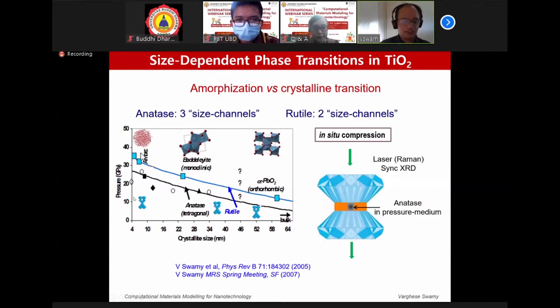And eventually it amorphizes. But if you start with a slightly coarser anatase nanoparticle, what happens is that the structure straight away transforms to the monoclinic structure, the high pressure phase. So this is a crystal to crystal transition, here a crystal to amorphous transition. Now, if you go to much coarser size, bigger than 50 nanometers and up to micro particle size, if you squeeze anatase in this diamond cell, you will see it transforming at lower pressure to the alpha PbO2 structure, which is the correct transformation as predicted by thermodynamics. So we are able to see three size channels here. And if you start with rutile, another phase, you find two channels, but not the amorphous phase.